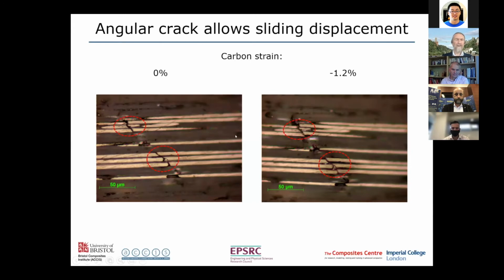And if you look at higher magnification, you can see that unloaded, those fibres line up approximately. But when you put them under load, you can see that they displace this way, but because of the angle, there's also a displacement in this fibre direction. So that produces a bit of additional strain. That's what gives us this pseudo-ductile strain that we get in compression.